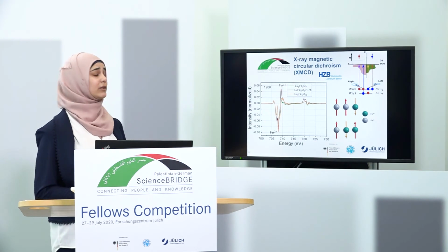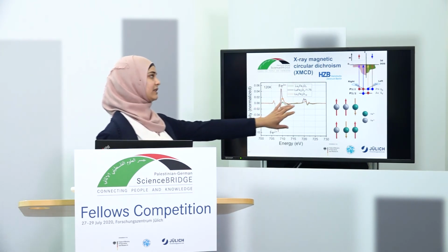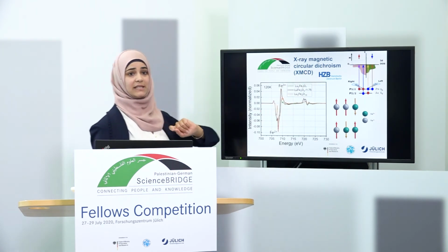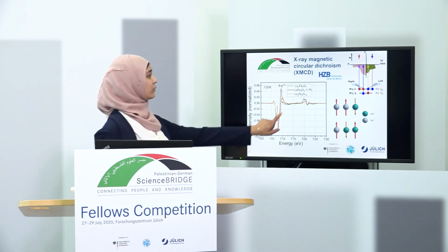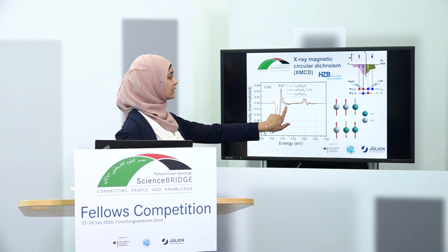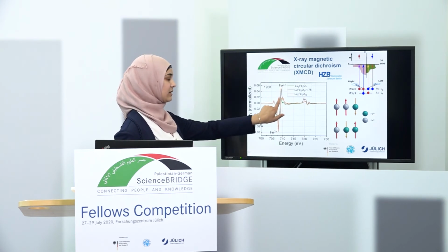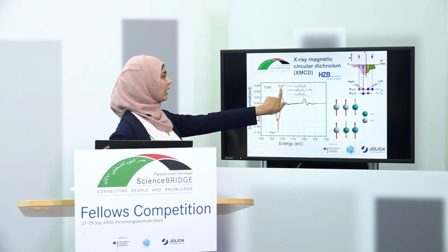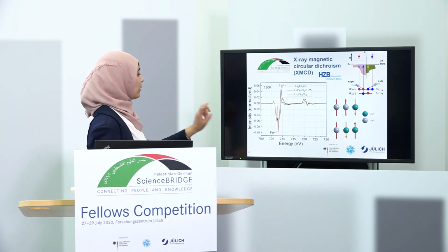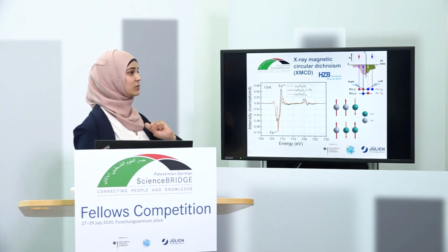Of course, this was done at the synchrotron at the high field diffractometer. The main message here, if I compare it with the 124, is that you have two peaks. This is the reason why we do the XMCD: we want to resolve the valences of the iron +2 and +3. So we have these two peaks, the upper one Fe +3, and the lower one Fe +2.